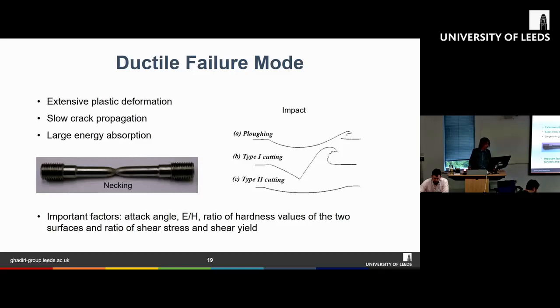And here's a typical example, showing the necking of a metal rod. If you pull it with enough force, this necking will start to form. And on the right, these are some typical examples showing impact failure of these ductile materials and how they behave under different stress. The important factors which affect ductile failure are the attack angle, the ratio of the Young's modulus and hardness, the ratio of hardness values of the two surfaces, and the ratio of the shear stress and the shear yield stress.